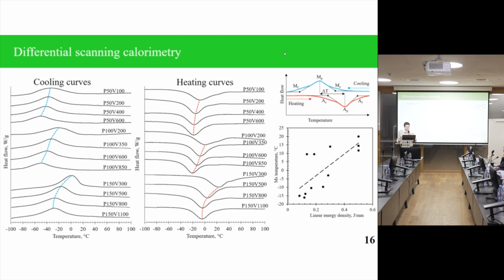We can see on these DSC curves, which were separated into cooling and heating curves, that all regimes caused shifting of the martensite and austenite peaks to higher temperature. And interestingly, for the case of high laser power, we observe a more rapid shift. And again, we clearly see the dependence of the transformation temperature on the linear energy density.